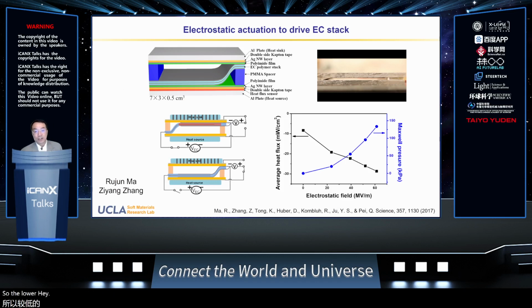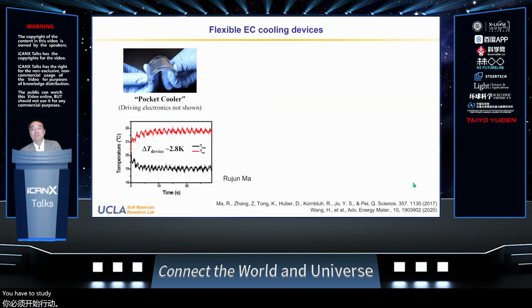The lower right chart shows the average heat flux under the same EC operation condition, the black curve there. As the electrostatic field is increased, the compression force between the polymer and substrate is increased, so the heat flux is increased, from 0 volt actuation to 60 volts per micron. You see that the heat flux is increased by more than 3 times with the electrostatic force. And this electrostatic actuation does not add any significant mass or volume to the device.